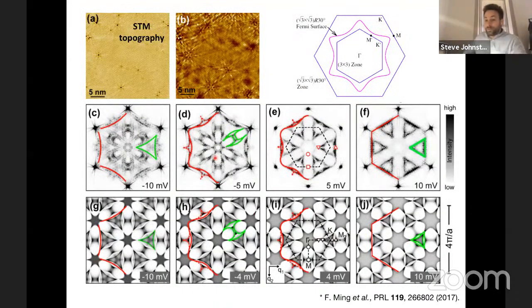So these are the experimental measurements of the quasi-particle interference. Again, this is a topography map. These are density images, and then these are the Fourier transforms of those density images as a function of bias voltage. Okay, so these are the experimental values here. This, to remind you, is what the non-interacting Fermi surface should look like. And so here, this is in the doped substrate, the most heavily doped substrate. What we see is that there are these arcs in the quasi-particle interference that kind of look like a 2kF image of this Fermi surface. That's what we can actually link back to the Fermi surface. There's also these dumbbell-like patterns. These are actually coming from Umklapp processes. Basically, if you replicate the Fermi surface around these Bragg peaks, these are where the arcs of the Fermi surfaces would be going. And so what's happening is the Fermi surface is large enough that you're starting to see some backfolding processes. And so it's a little bit difficult to deconvolve what the actual band dispersion is doing here. But nevertheless, as you sweep the bias voltage up, you can see that this guy starts to creep inward.